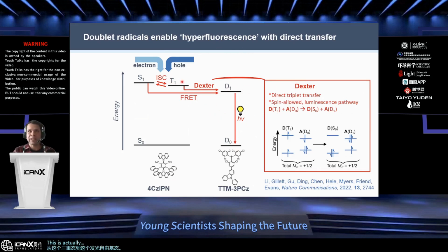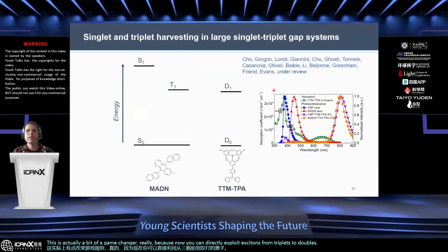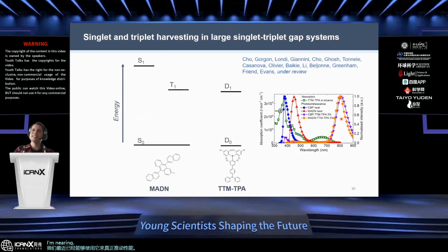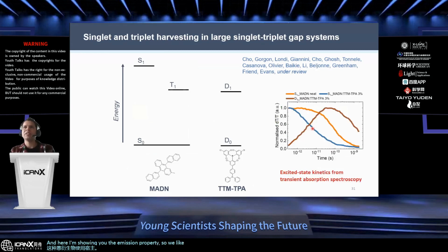This is actually a bit of a game changer, really, because now you can directly exploit excitons from triplets to doublets. And we've been able to employ this recently to really push the performance of near-infrared devices using this material here, another radical dye with another TTM with a hole transporting material, here combined with this anthracene derivative used as the host. And here I'm showing you the emission properties. So we lined them up for energy transfer.